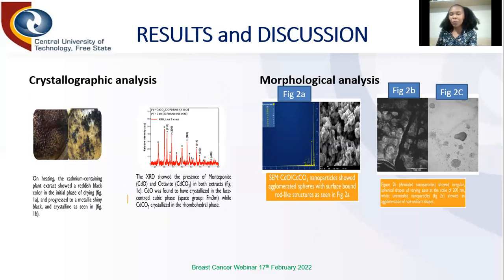But before we get to that part, we will firstly discuss the results from characterization. Whilst heating the nanoparticles in the oven after synthesis, in figure 1, we observe the crystallinity. Yes, and this interestingly is also confirmed by the X-ray diffraction, whereby the cadmium oxide nanoparticles were found to have crystallized in the face-centered cubic phase, whilst the cadmium carbonate crystallized in the rhombohedral phase. So this shows crystallinity. And of course, the XRD has confirmed the formation of cadmium oxide, cadmium carbonate nanocomposite.